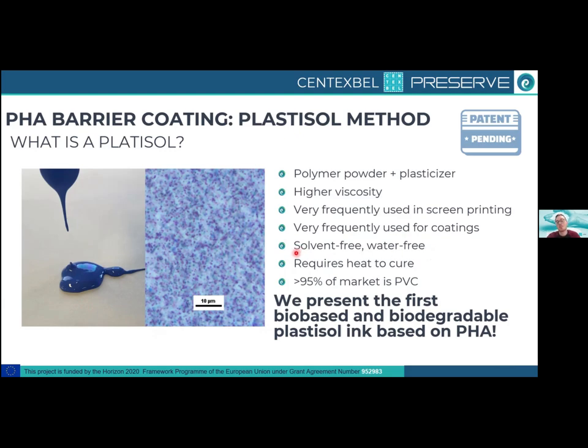And the main reason why it is important to use PHA in this plastisol is not only to make it fully bio-based, but also that more than 95% of the market right now is PVC. So making not only a bio-based, but also a biodegradable plastisol that is based on PHA is possible.